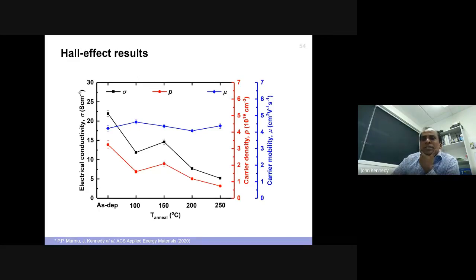This is the kind of interesting thing. Up to 100, 150 degrees C, the electrical conductivity is going down, obviously, when you anneal longer. But as I said, copper iodide is mostly good as deposited and up to 100 degrees Celsius. So you need to find the proper phase to have a stable and reasonable conductivity and Seebeck coefficient. And if you see, mobility stays, the blue line, which is a good sign. Mobility is not changing. It's only your carrier density that is changing, but not much if you go from as deposited to 100.